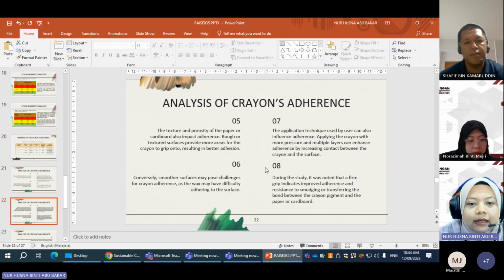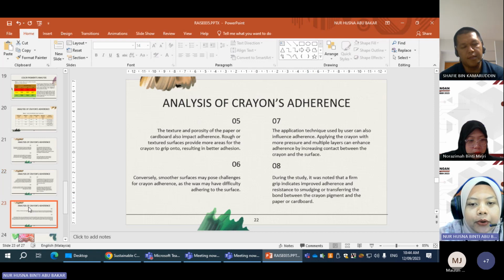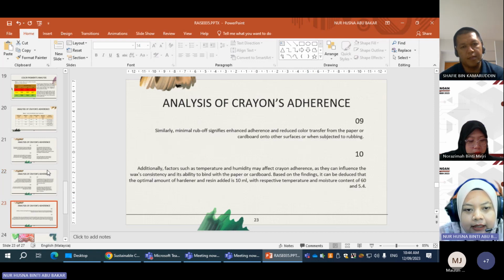So during the study, we can conclude that a firm grip indicates improved adherence and resistance to smudging and transferring, a bond between the crayon pigment and the paper or cardboard. Based on the findings, we can deduce that the optimal amount of hardener and resin added is 10 ml, and the respective temperature and moisture content are 60 and 5.4.